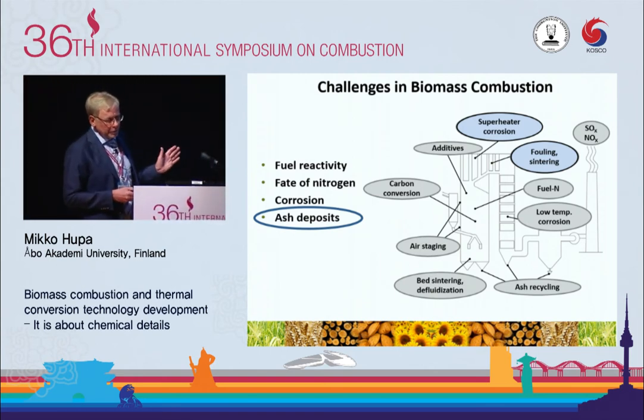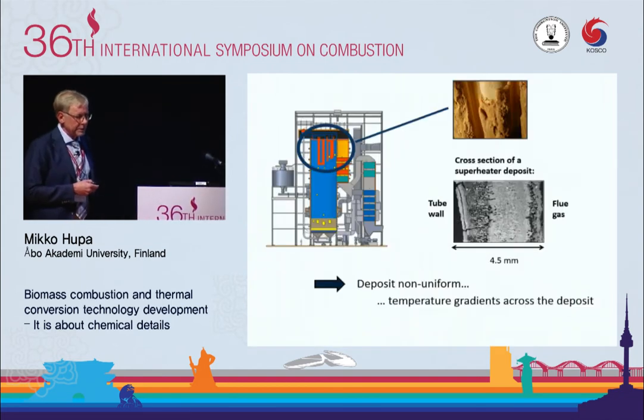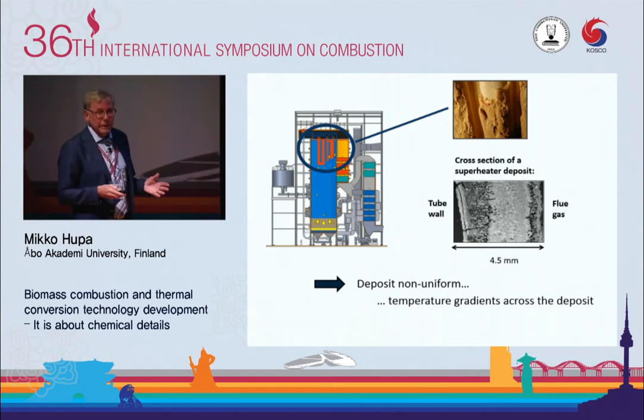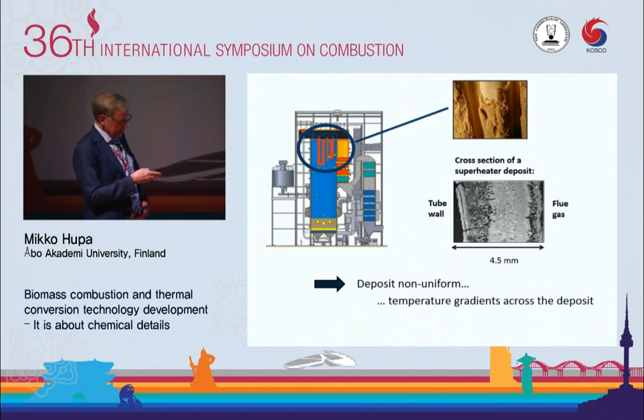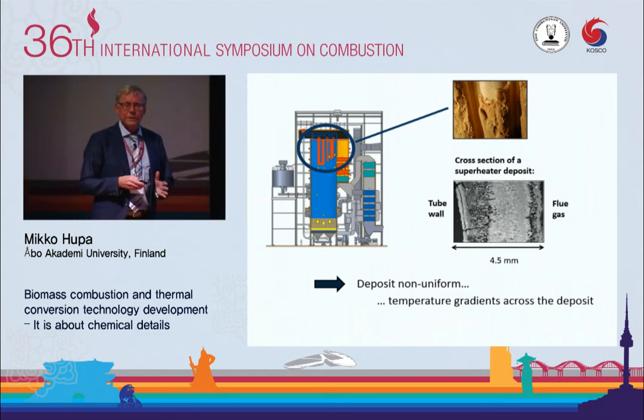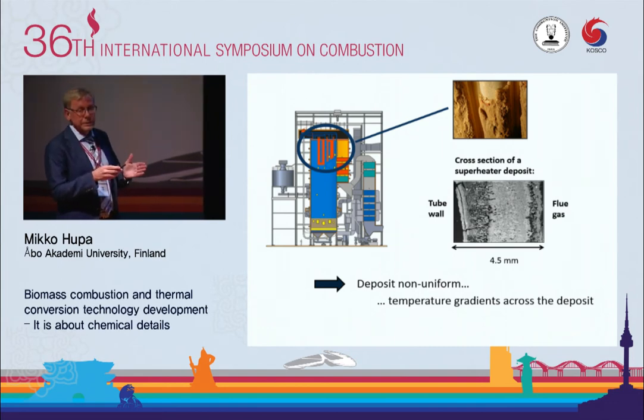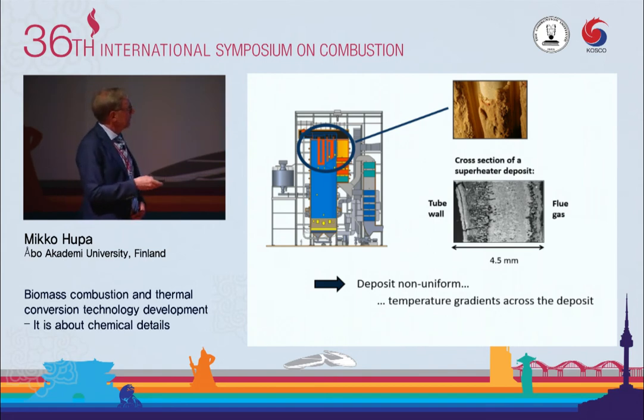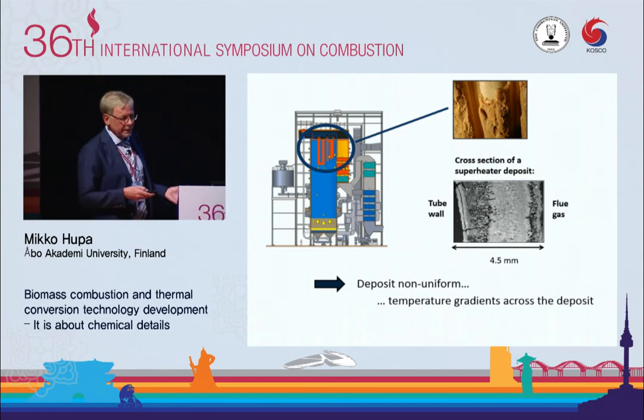Now a few words about ash deposits. Corrosion is one aspect, but then the whole fouling issue is also another one. And one detail we were interested in, that we know that when we sample ash deposits, either with probes or from the boiler, we see that the deposits are not homogeneous. They look different on the tube surface as compared to flue gas. And it's quite obvious because there is a temperature gradient across the deposit. There was a lot of discussion about how does this temperature gradient influence the deposit with time. There were speculations, maybe something happens. And we were wondering if we can study that in the laboratory.